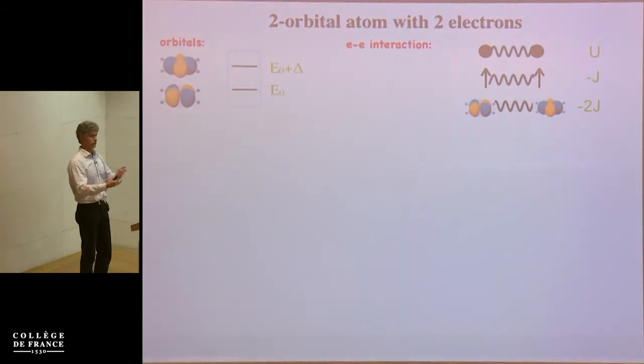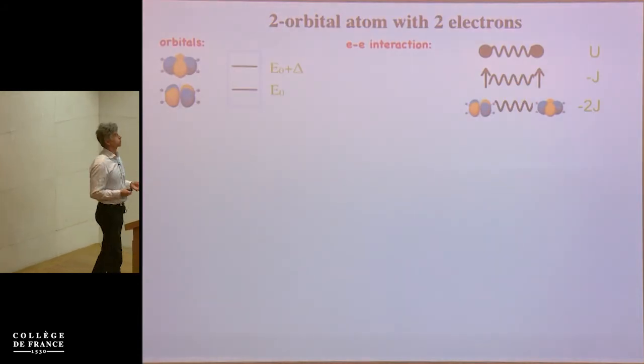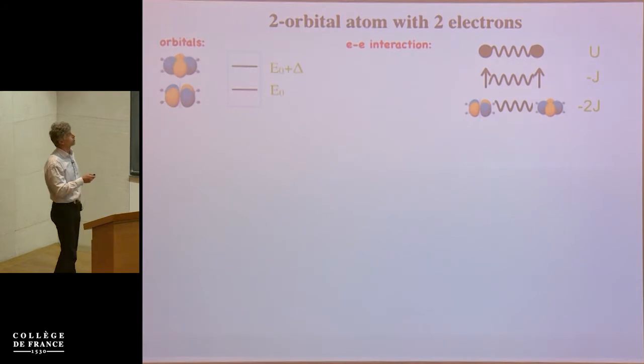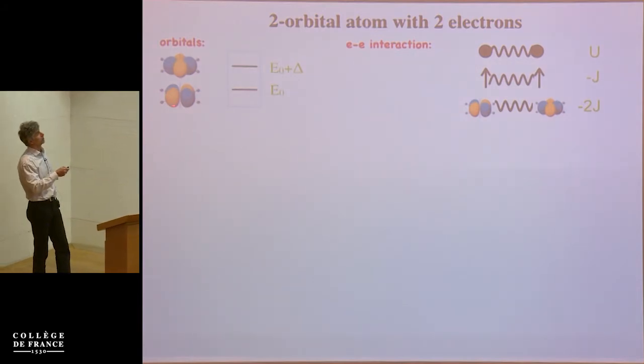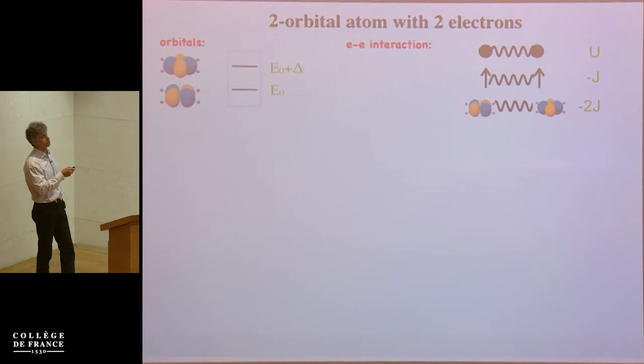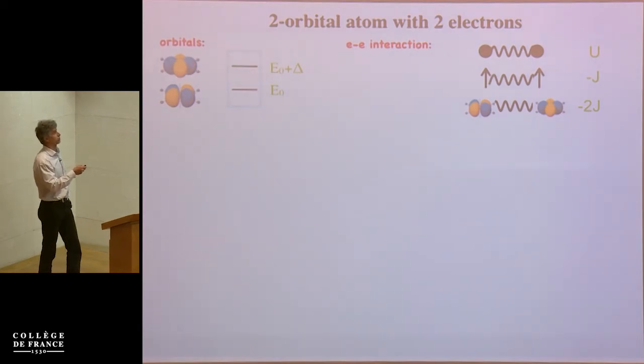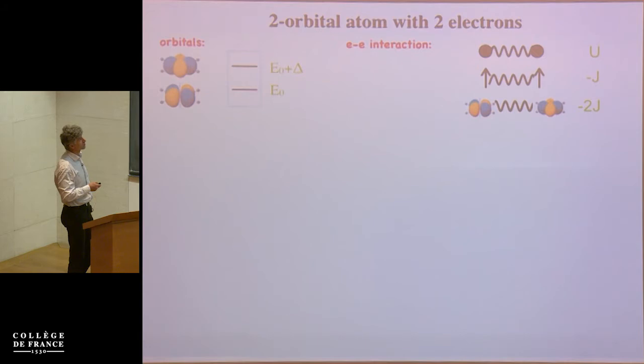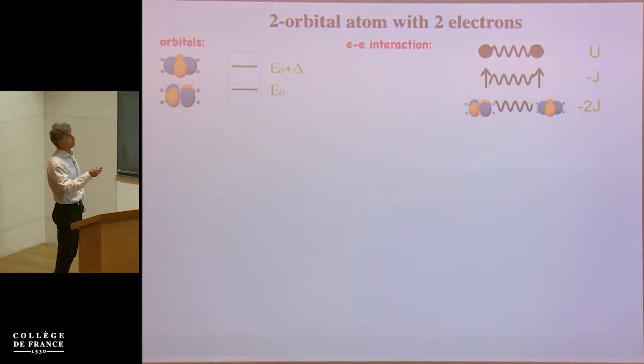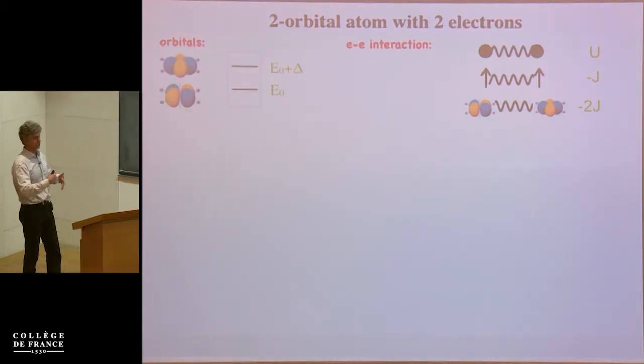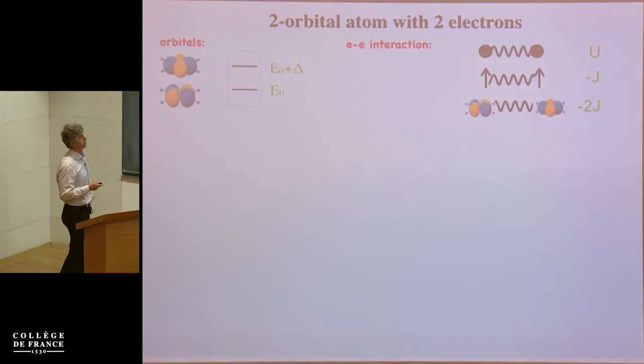So to get several different multiplets, we need at least two orbital atoms. So we start with two orbital atoms where we have some crystal field splitting between the two orbitals. You can think geometrically about these x squared minus y squared and xy orbitals. And we'll consider the local electron-electron interaction, including the Hund's ferromagnetic coupling.